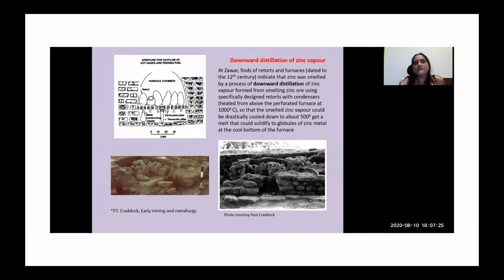And due to this condensation process, the vapor is able to be condensed into the liquid state, and then it solidifies into what look like droplets at the bottom of the furnace. So this was quite an ingenious way of actually extracting the zinc in the metallic form. So basically, you had a temperature gradient of about 500 degrees so that the melt could solidify into these globules at the bottom of the furnace. And as you can see there, you see the perforated plate.